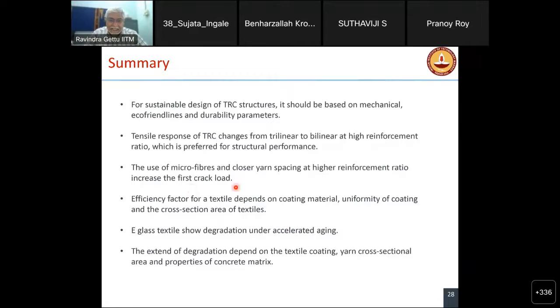If we want to use the first crack load, we can use close yarn spacing and microfibers. We have defined an efficiency factor which is independent of the volume fraction or the number of layers. So once we do the test, we don't have to keep on repeating the test for number of layers. With a certain number of tests, we can get the efficiency. The E-glass is something we have to work on. It is cheaper, it is more readily available. So if we can reduce the degradation, we know that there is degradation. We have determined it under accelerated aging. But if we can find a way to slow down the degradation, that would really help. And the extent depends on many things like textile coating and fibers and so on.